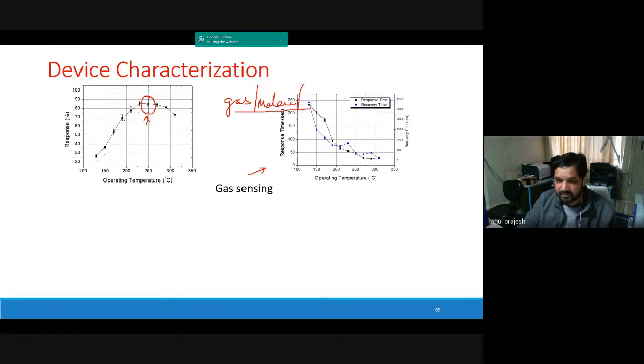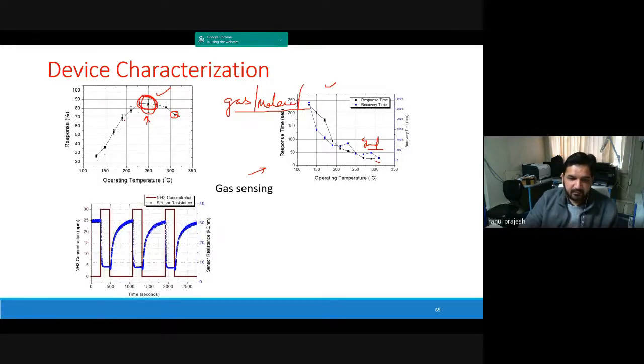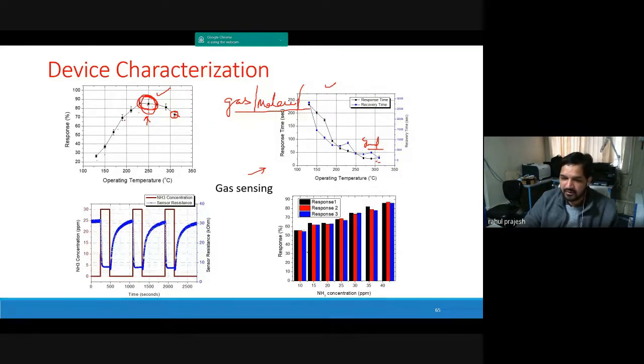Response and recovery time will reduce with increasing temperature. This is good, but you need to have a trade-off, because if you increase the temperature further, in this particular case, if you see 300 degrees centigrade, the response time and recovery time are fast, but the response is low. So you need to have a trade-off between response and the times. You can choose somewhere around these values where you get the maximum response. Then you can check the repeatability of the sensor by giving multiple pulses of the gas, and then finally you calculate the input concentration and the response you are getting, and it should be linear.